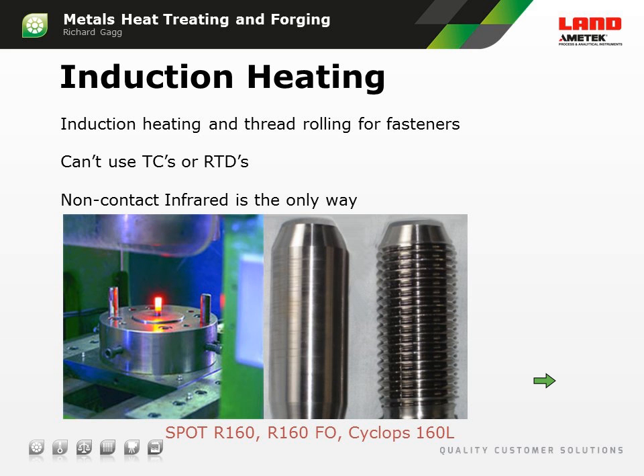And in these cases, the blank, which is this piece here, is heated in an induction field. And then once it comes to temperature, and it has to be the exact temperature, which is why they're measuring temperature, then the thread is rolled into the surface. It's not cut, so it's not cut with a die. It's actually rolled into the surface, and so there are no imperfections or cracks on the surface that may cause the fastener to fail. And so this is why when Boeing buys a fastener, it pays $15 and not 15 cents.